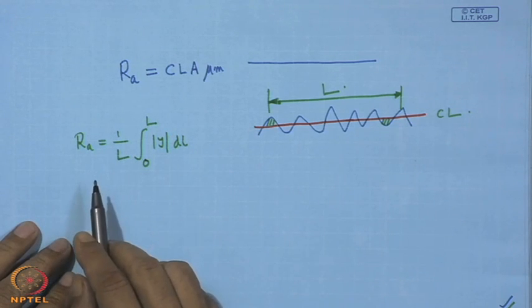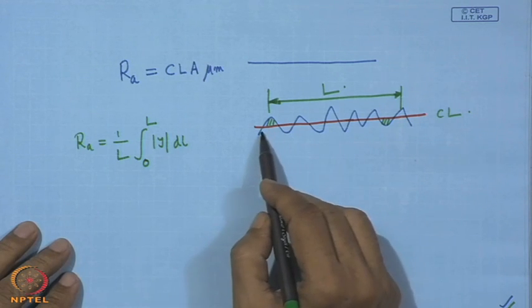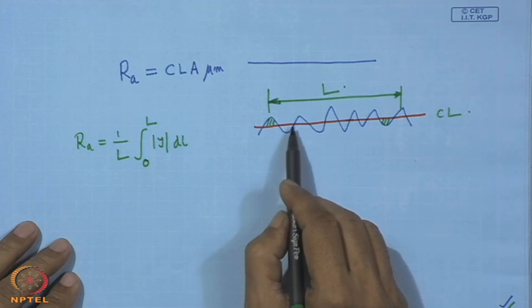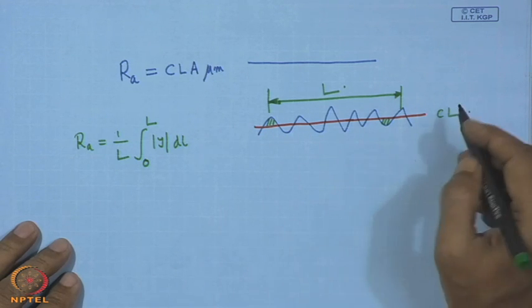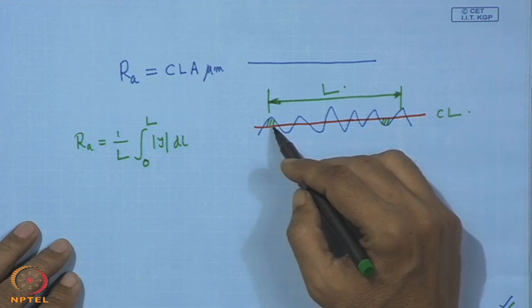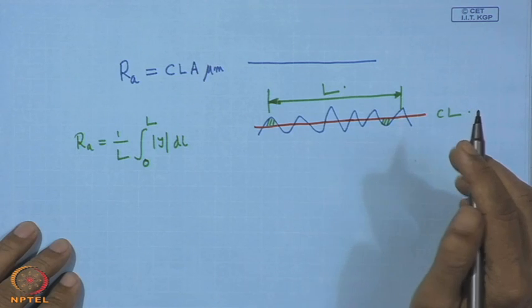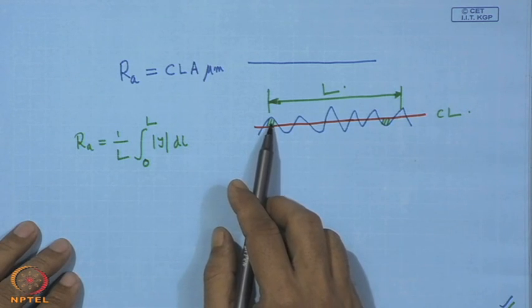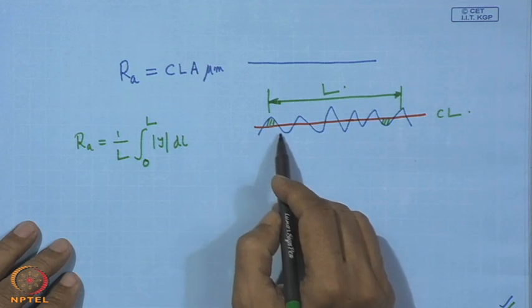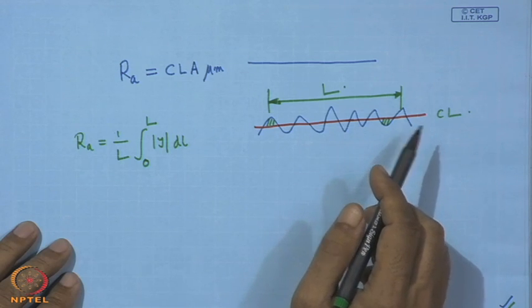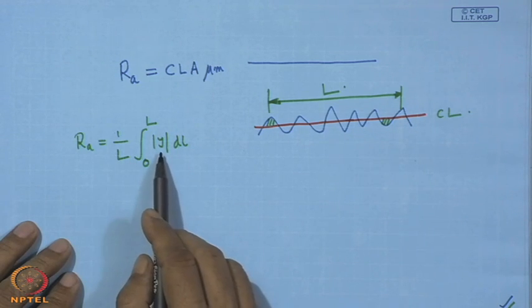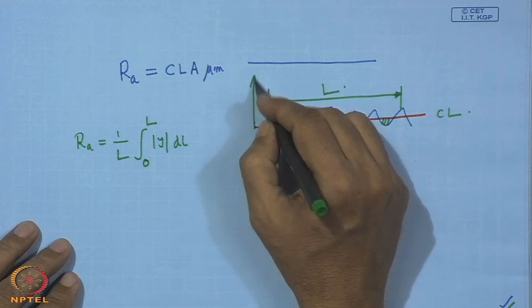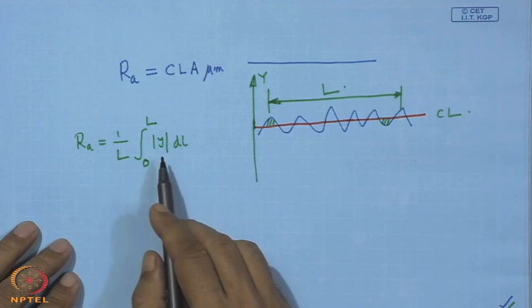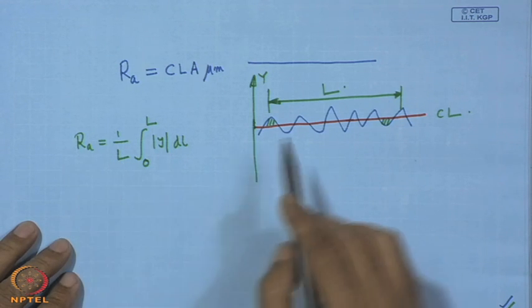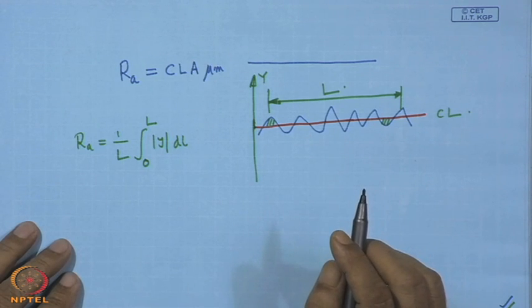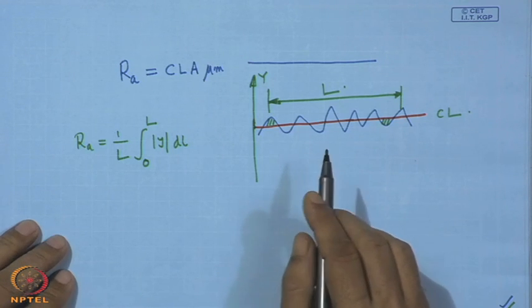What is the significance of this one? It actually shows the departure of the blue line about this red one, which is the center line, and it is defined so that the equalization of the areas above and below is properly done. And here it is actually the arithmetic average of the total departure of this actual surface from the mean line, and that is given by this equation. So, here this is actually the y direction, so we consider only the magnitude. From there we can get the average deviation from the mean line. So, this is one of the parameters which is expressed to define the surface roughness.